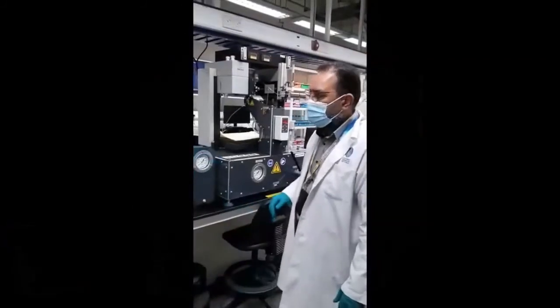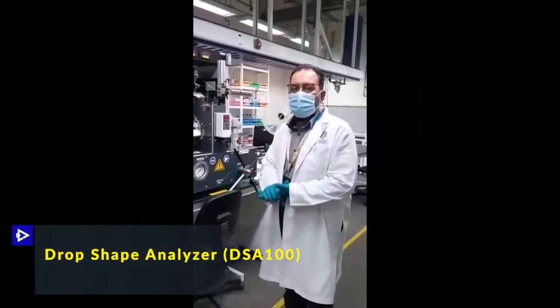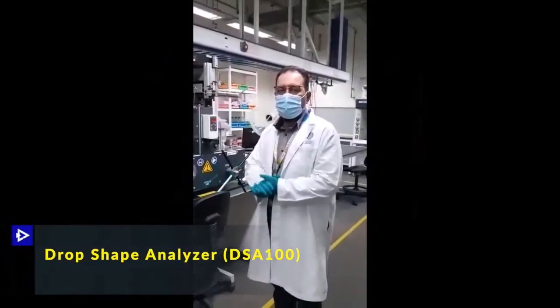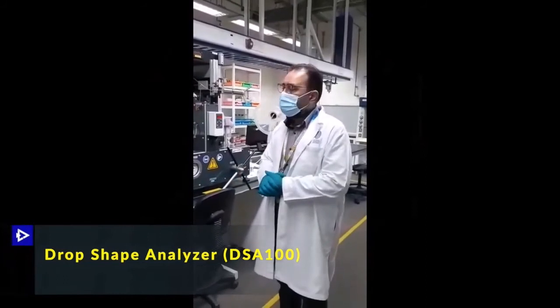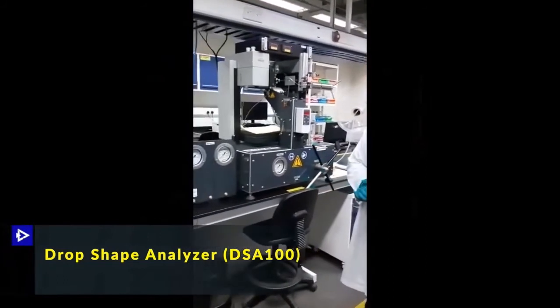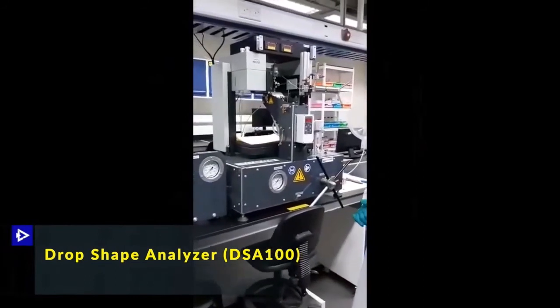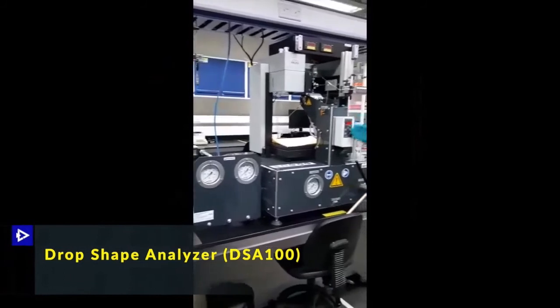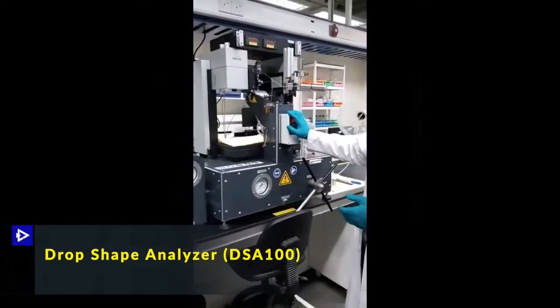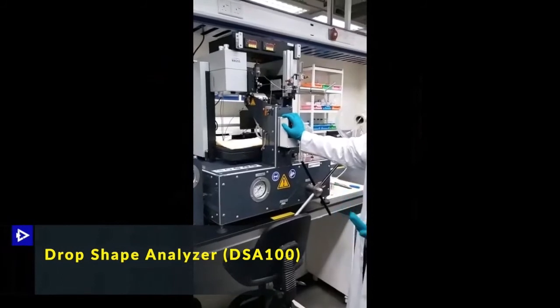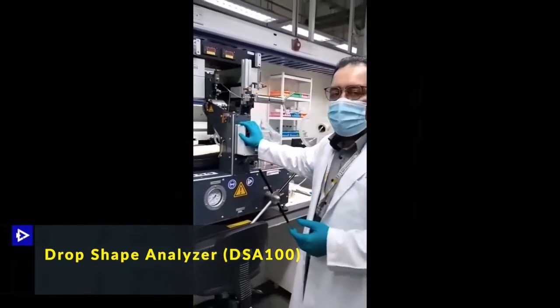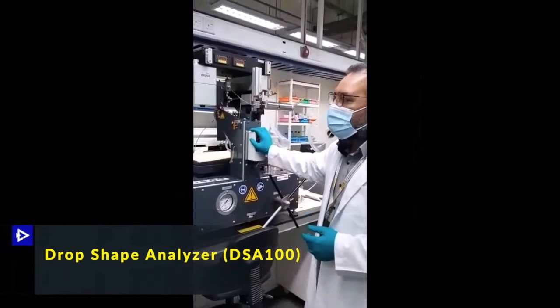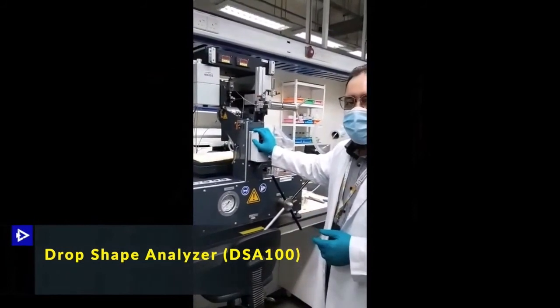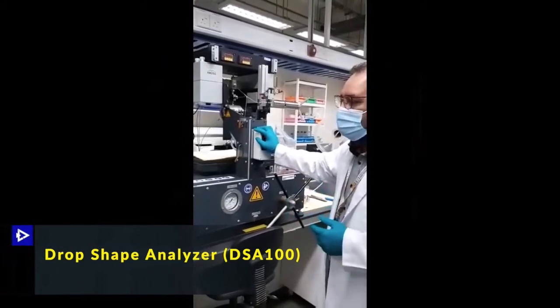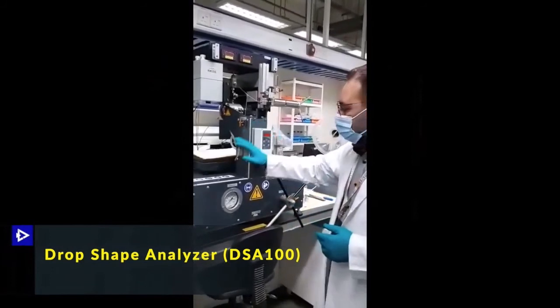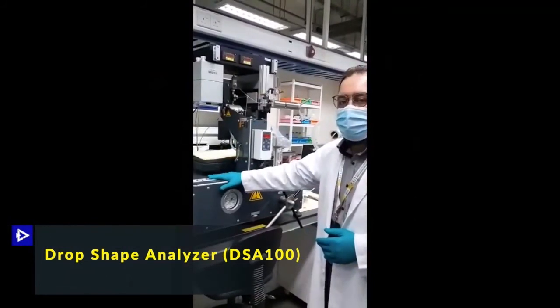The DSA-100 measures the contact angle, surface tension, and some of the other physical properties of the shale material, and also other porous materials that we have. In this equipment, we can go up to different temperatures, up to 60 or 80 degrees, and also very high pressures, such as 300 bar, 30 megapascal, or even slightly more, which is very unique equipment, and we can find it as iconic in the study of physical properties of shale and porous material all over the world.